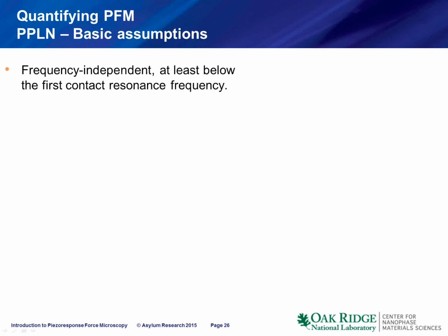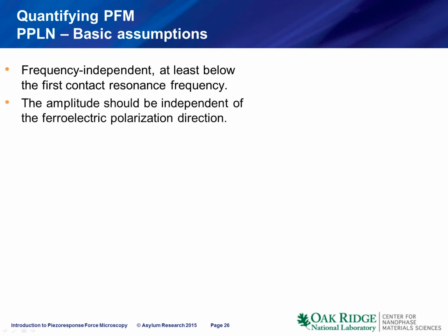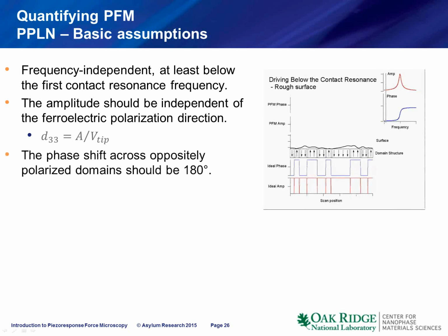It's a uniaxial material with the polarization direction in or out of the plane. We're going to assume that this material should be more or less frequency independent, at least at PFM frequencies from 10 kilohertz to maybe a couple megahertz, certainly below the contact resonant frequency. The amplitude should be independent of the domain orientation, so we expect the same amplitude when the polarization is up or down, which means that the D33, or the D effective that we measure, defined by the amplitude divided by the tip voltage we're driving at, should be the same over the two domains, and that the phase shifts across the domains should be 180 degrees.